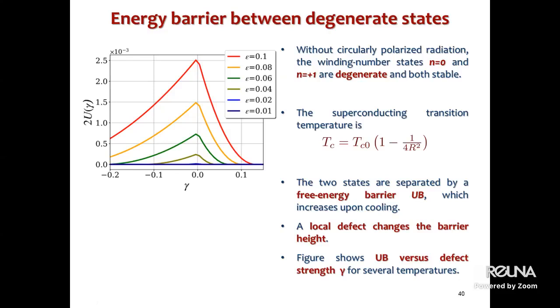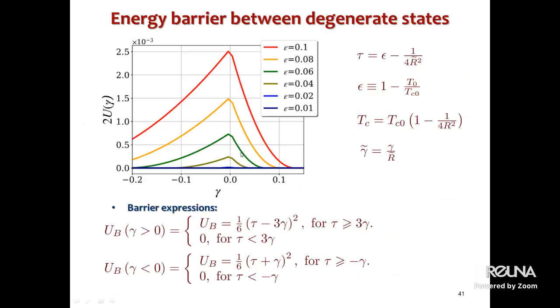The two states are separated by a free energy barrier, and when we do not have any defects, we follow this zero line, and we see that the barrier increases upon cooling. So increasing cooling increases the barrier. But a local defect changes the barrier height. So either we go to the right or to the left, we change the barrier height. The figures show the free energy barrier versus defect strength for several temperatures. And the mathematical expression for the barrier is given here in dimensionless units.